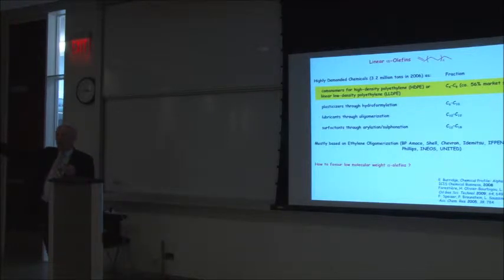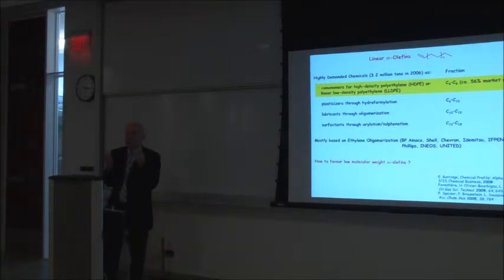So if you want to make polyethylene, you don't want any elimination to proceed. You want to go straight to the end, incorporate as many ethylene molecules as possible. If you eliminate the growing chain too early, you just make a dimer, C4. So you have to balance in between. To make C6, C8 is very challenging. The energy differences here are just a few kcal per mole, and that will dictate whether the catalyst is suitable or not.